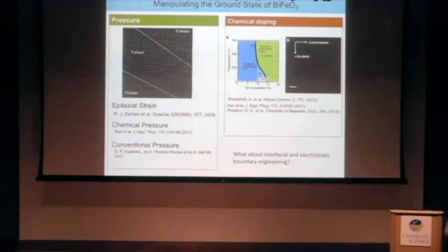Now, the important thing here for what I'm going to talk about is that I'm going to mention magnetism a bunch because I do neutron scattering. Through this whole phase, as far as we know, it's a G-type antiferromagnet, where in the thin film case you kill the cycloid for most strain states. In this case it's also just a normal G-type. But the tilting patterns are different going from the rhombohedral state to the orthorhombic state.